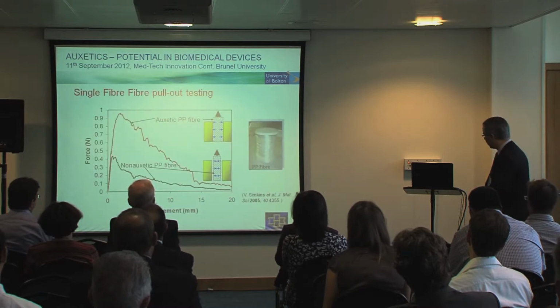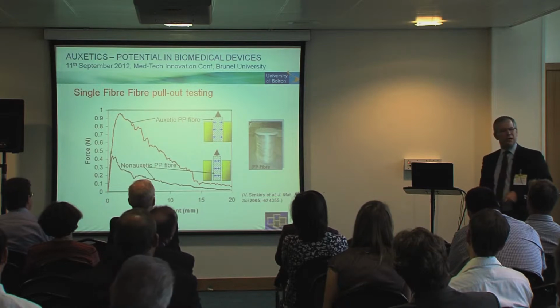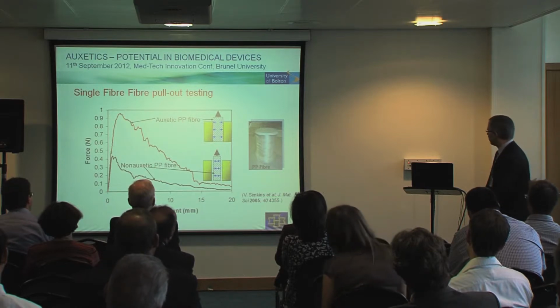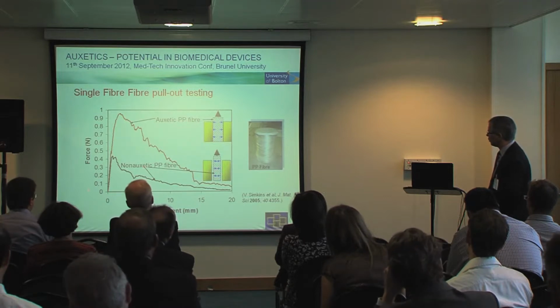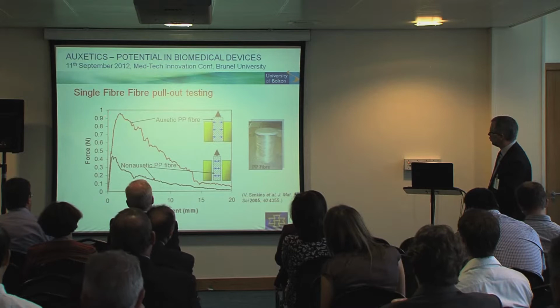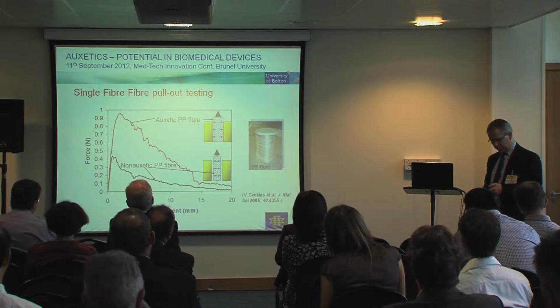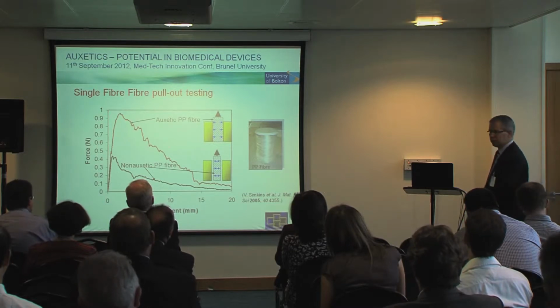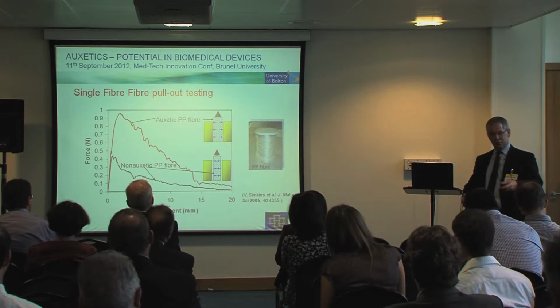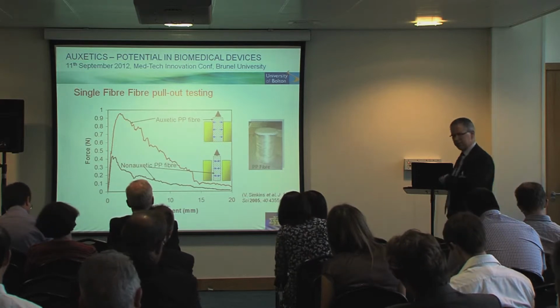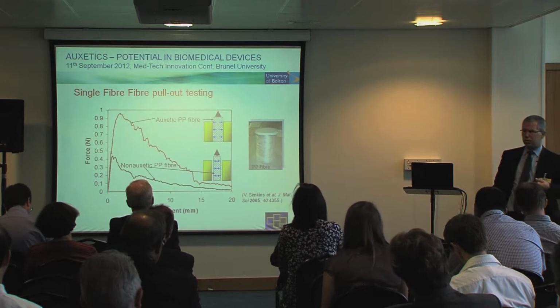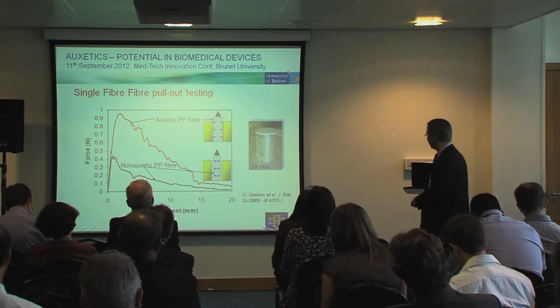Well, we made the world's first auxetic fibres a few years ago, and we're able to show in single fibre pull-out tests that this indeed works. So this is a single fibre pull-out test on auxetic and non-auxetic PP fibre samples, and you can see that the auxetic sample can withstand twice the maximum force, and the area under the curve tells us 3 times the energy is required to pull that out. So this anchorability effect, and therefore potential in sutures and ligament devices and so forth is there.